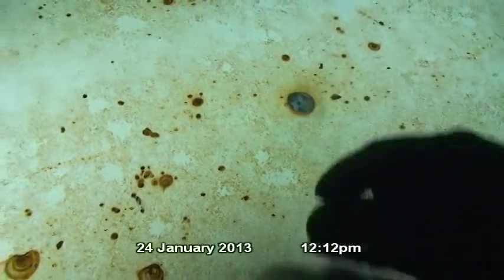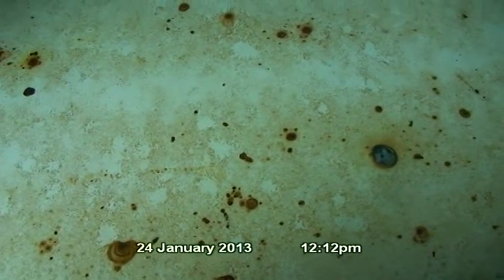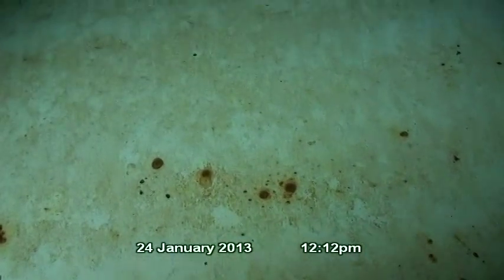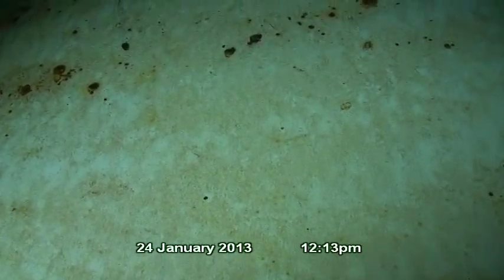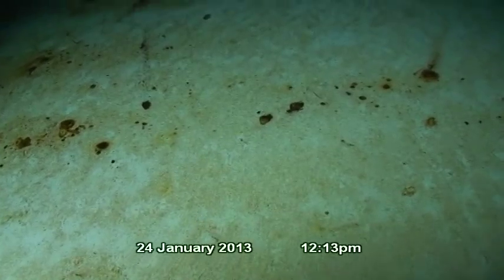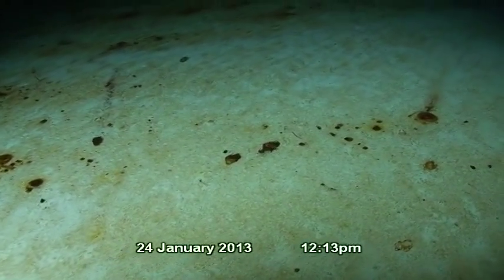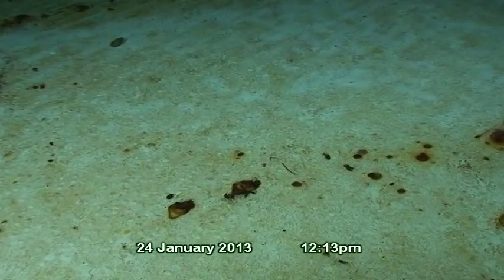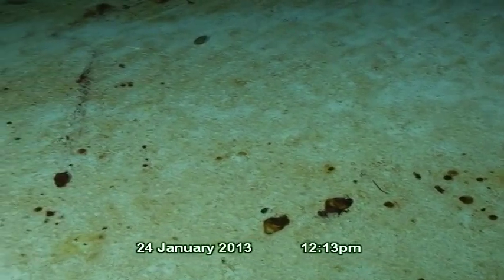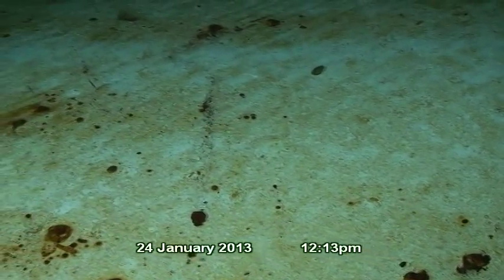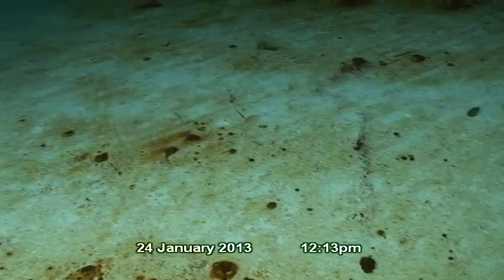Slight metal loss is taking place in this area. This appears to be representative of the metal loss that is taking place on the interior of the facility. In approximately a third of the areas investigated, moderate metal loss was taking place. In a third of the areas, slight metal loss was taking place. And in the other third of the areas, metal loss was not taking place.